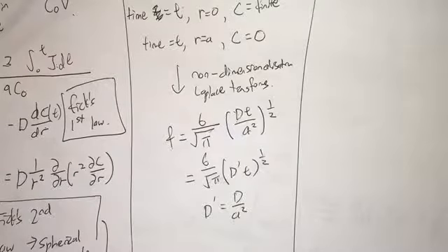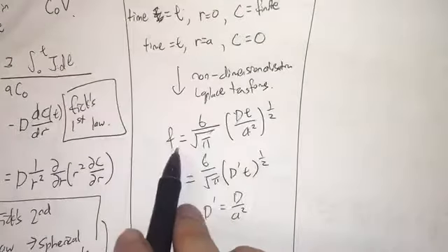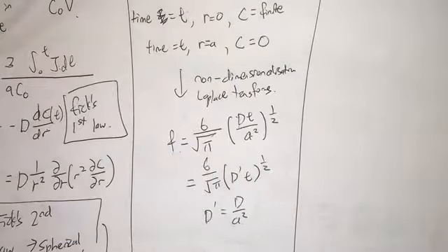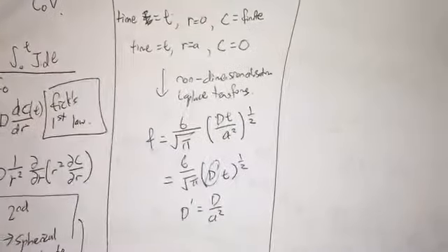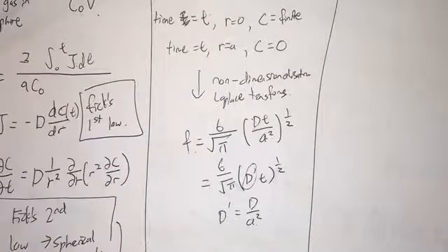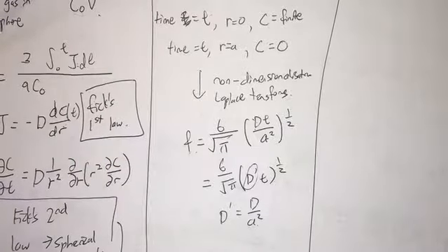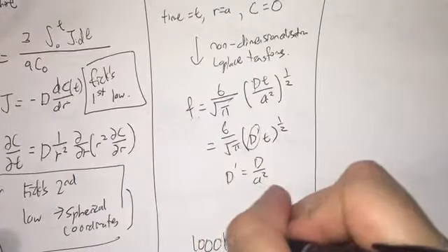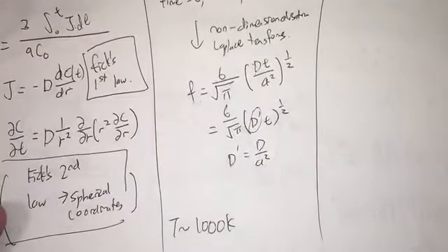So this will help us to represent the release of gas over time at some temperature. So plotting F versus T to the power of half, the fractional release to the T to the power of half, we can find this D prime, and that helps us to fit it back into our model, so as to hopefully predict. Anyway, this is assuming a fixed amount is trapped and now is released by increasing the temperature uniformly, and usually this temperature is about 1000 Kelvin for this diffusion process to happen.